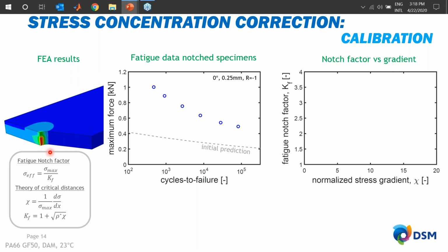And to calibrate that model, the only thing that you need to do is find a certain Kf value, compute a certain normalized stress gradient, and then you can fit a certain characteristic length. And in practice, it looks like this, because first you underestimate, but you have measurements. That means you can manually shift your curve through your data points. You can see that we try to focus on the high number of cycles, and we are underestimating the lower number of cycles. But I will come back to that in a second, because this has to do with plasticity that we can also solve. But we decided to focus always with this calibration on the higher number of cycles.